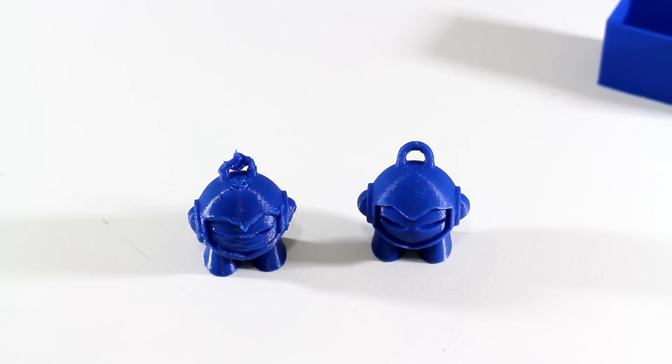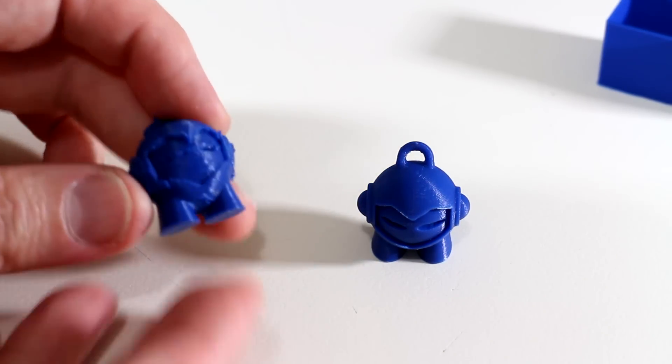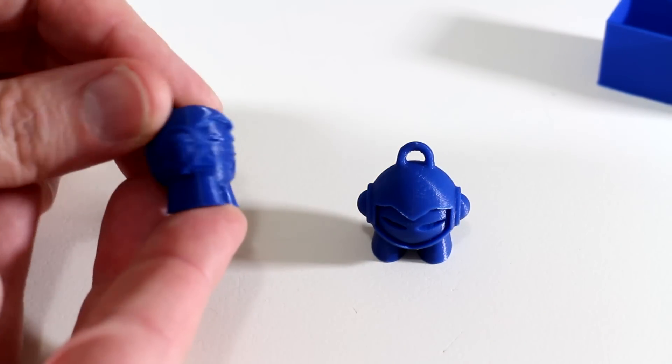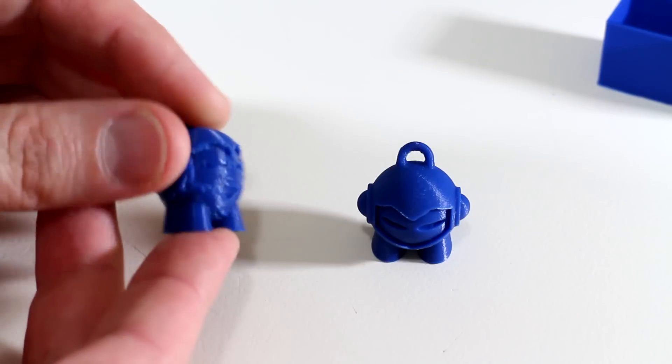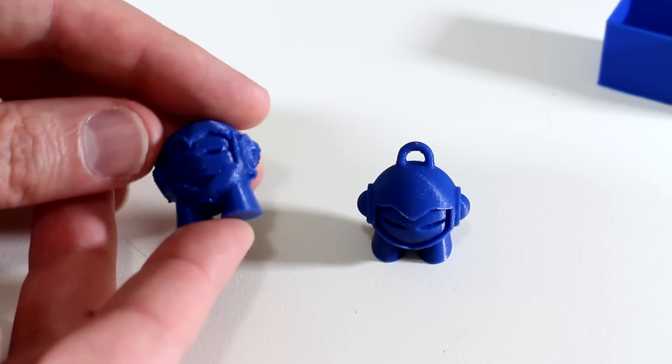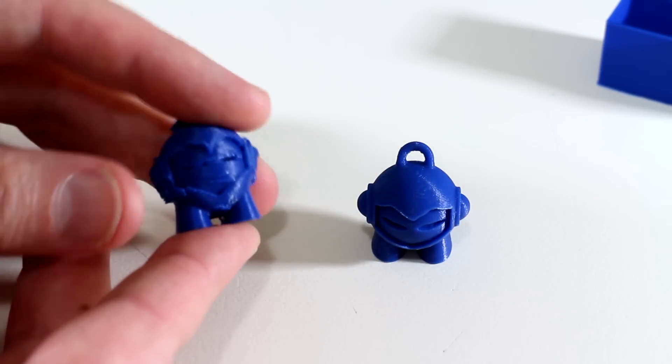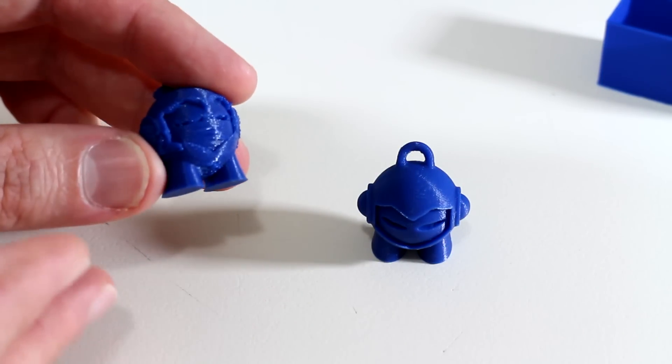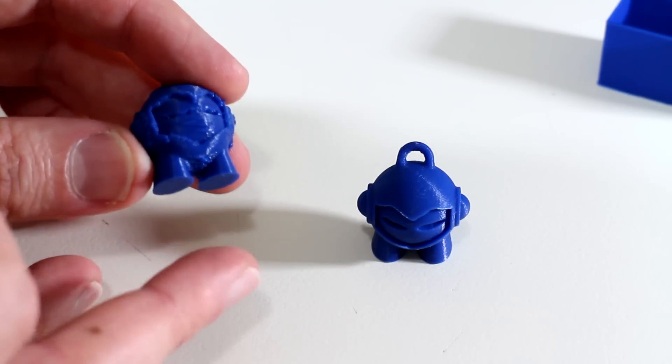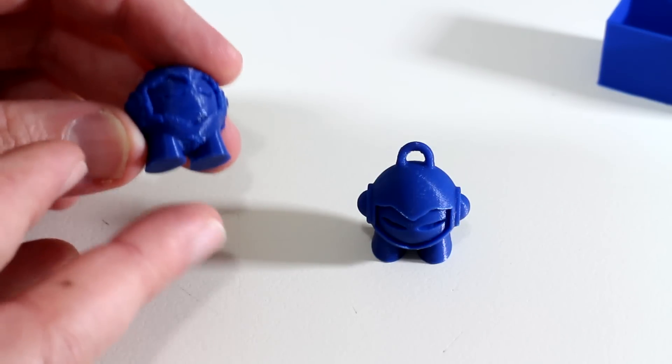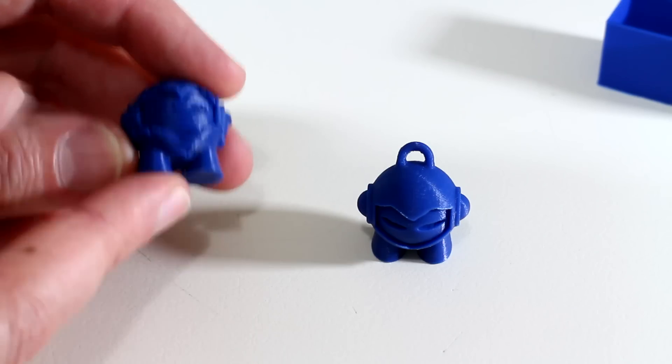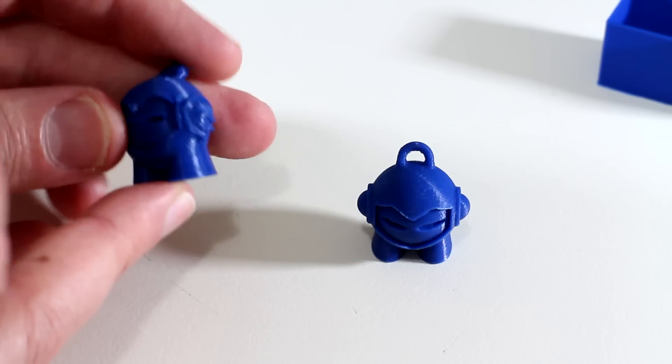So this is what happens with PLA plastic without the cooling fans. PLA has a glass transition temperature of approximately 55 degrees Celsius. So the cooling fans assist in cooling down the plastic to that 55 degree mark before the next layer gets deposited.